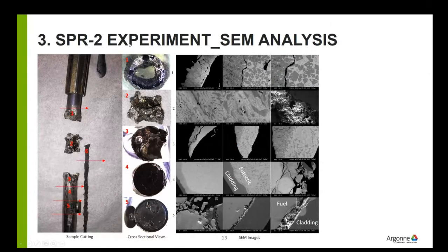And this slide shows the SPR2 experiment SEM analysis. So this picture shows the disassembled test section of the SPR2 experiment. You can clearly see the disrupted fuel claddings due to the eutectic formation. We cut the sample as shown in this picture to have SEM images of each sample. This picture shows the cross-sectional view of each sample, and on the right side, SEM images of each sample are shown. To the right, inside these SEM images, the magnification is increased.